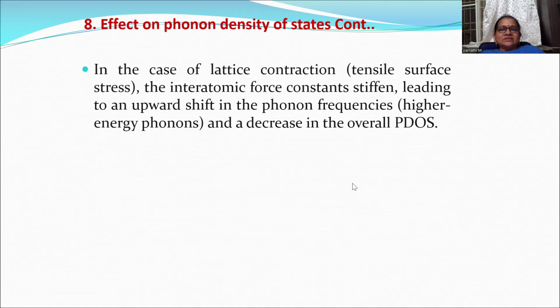In the case of lattice contraction, tensile surface stress, the interatomic force constants stiffen, leading to an upward shift in the phonon frequencies. So higher energy phonons and a decrease in the overall PDOS. In the previous slide, we have seen that if the surface is contracted, interatomic force constants stiffen.